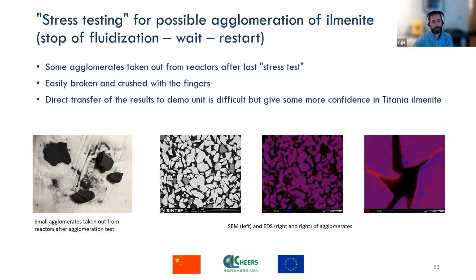And we sent some of these agglomerates for analysis in Oslo. And if you see on these EDS pictures, the red stuff on the surface here is iron. So this is known, that the iron tends to migrate to the surface of these ilmenite particles. And it seems like this is the thing that causes the particles to stick together.